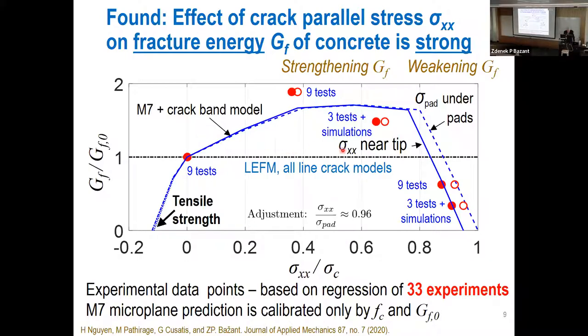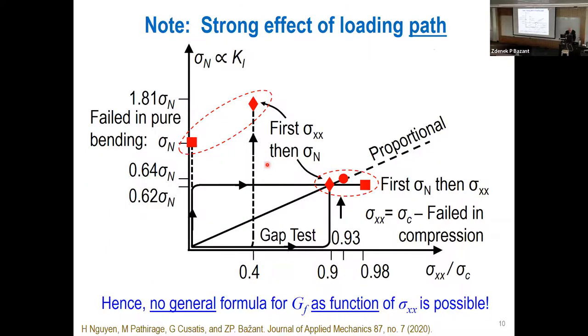I should say that this phenomenon is different for different materials, and this is for concrete. Now, you might think, okay, so in a code for the cohesive crack model or for LEFM, we just put a formula for GF depending on the stress. But that would not work because it's damage, and damage is enormously path dependent, more than plasticity, history dependent.